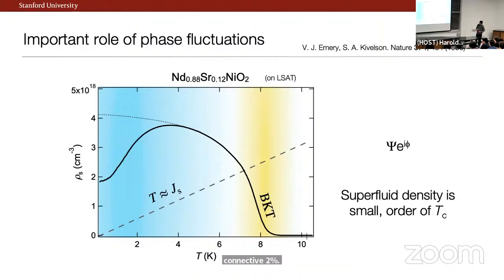Namely that the superfluid density is kind of small and on the order of TC. And I'm not doing justice to the ideas here, but let's say we had a normal electron-phonon coupled, well-understood superconductor. And I tell you that in the zero temperature limit, all the electrons are going superconducting. It kind of doesn't matter if TC is at 5 Kelvin or 10 Kelvin. If I go all the way to the low temperature limit, all the electrons are superconducting, right? But again, a characteristic of these sorts of materials is that that's not the case. And in fact, the TC seems to scale with the apparent measures of the superfluid density.